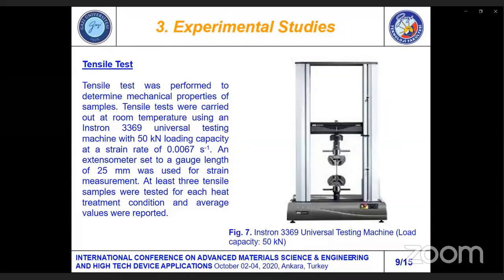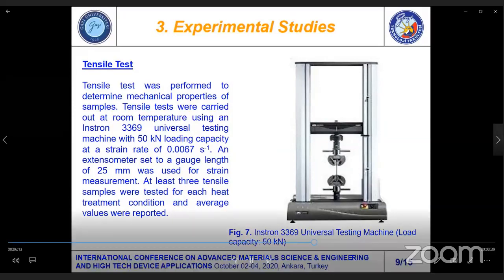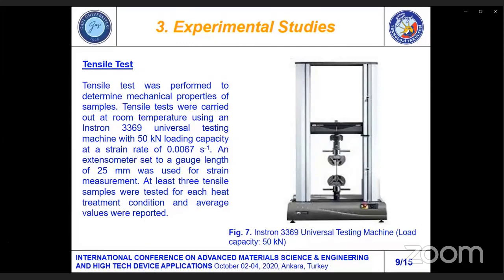Tensile test was performed to determine the mechanical properties of samples. Tensile tests were carried out at room temperature using an Instron 3369 universal testing machine with 50 kN loading capacity at strain rate of 0.0067 per second. An extensometer set to a gauge length of 25 mm was used for strain measurement. At least 3 tensile samples were tested for each heat treatment condition, and average values are reported in the paper.